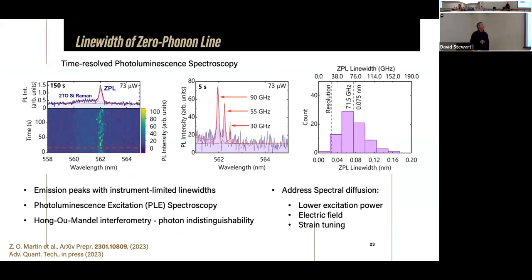And to prove that that's indeed the case, if you measure for 150 seconds, like 2 minutes, versus if you measure it only for 5 seconds, then you get much more narrow lines, going down to 30 gigahertz, which is already measurement limited width, so we basically cannot measure more narrow lines. And to find out eventually what is the width of these lines, as our next effort we're going to do photoluminescence excitation spectroscopy, which would allow us to obtain more narrow lines, and we would like to see how narrow they are. And eventually, what we're after is to see whether these single photons could be indistinguishable.